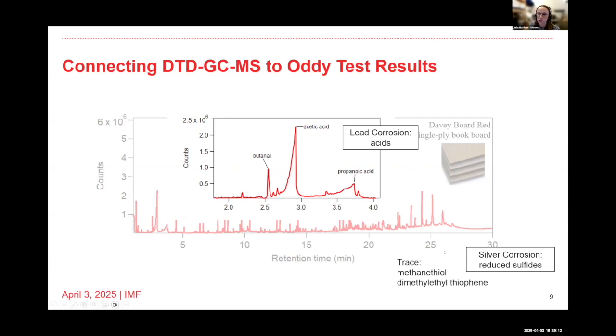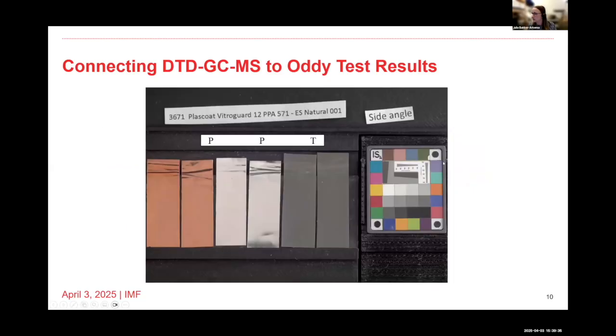And similarly, I don't show the zoom in for the sulfides, but we detected trace methane thiol, which is a reduced sulfide molecule, and dimethyl ethyl thiophene. And so we can start to draw these connections between, okay, what's the Oddy test result and which specific molecules are responsible for the corrosion that we're seeing. So this is a bad material.